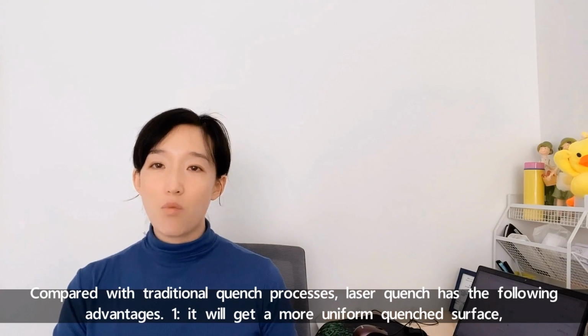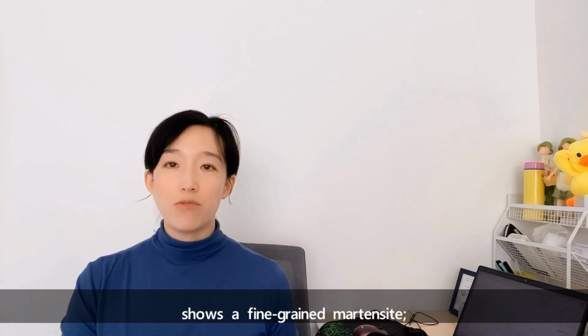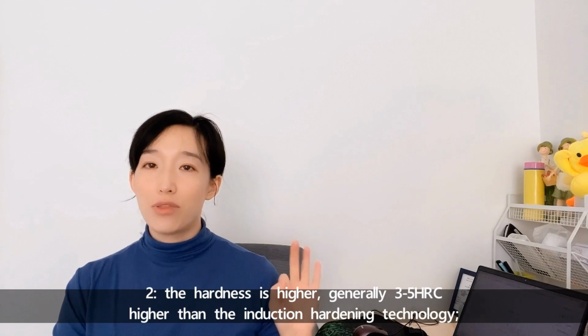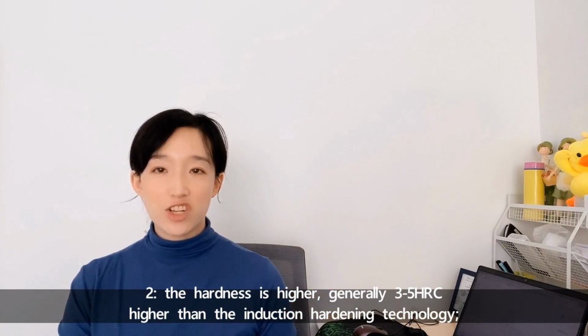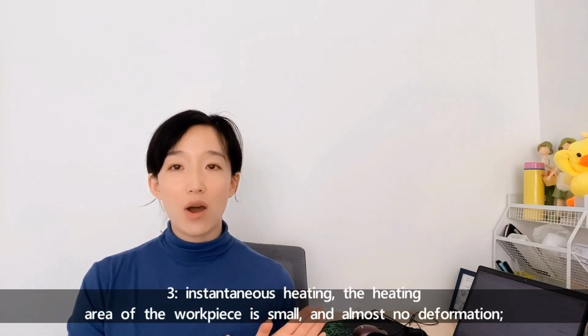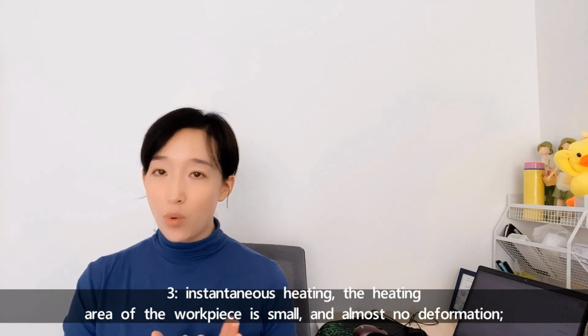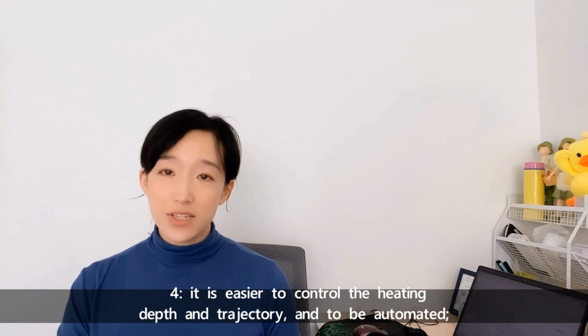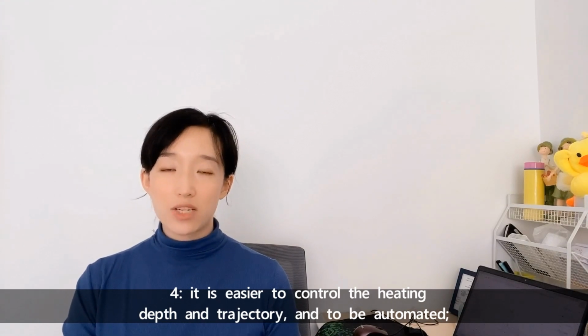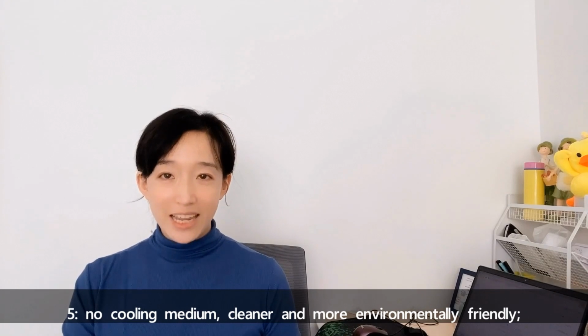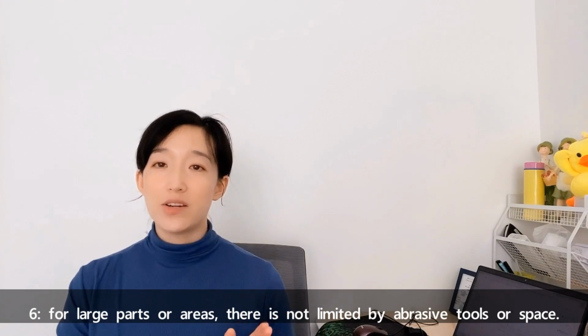First, it will get a more uniform quenched surface, showing fine-grained martensite. Second, the hardness is higher, generally 3 to 5 HRC higher than the induction hardening technology. Third, instantaneous heating. The heating area of the workpiece is small and there is almost no deformation. Fourth, it's easier to control the heating depth and the trajectory and to be automated. Fifth, no cooling medium, cleaner and more environmentally friendly. Sixth, for large parts or areas, it's not limited by abrasive tools or space.